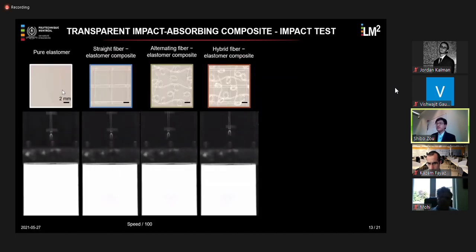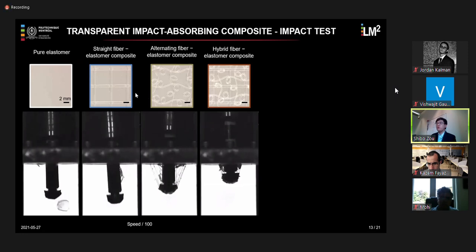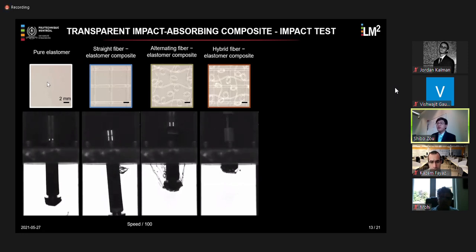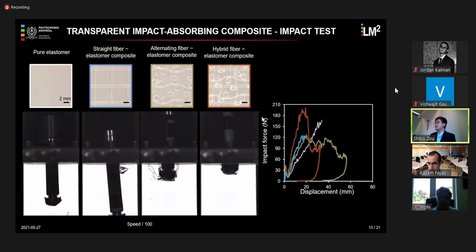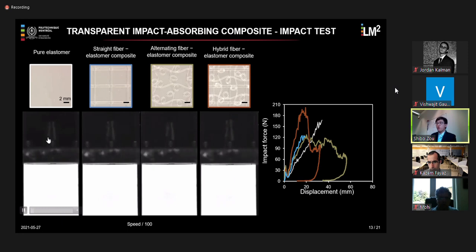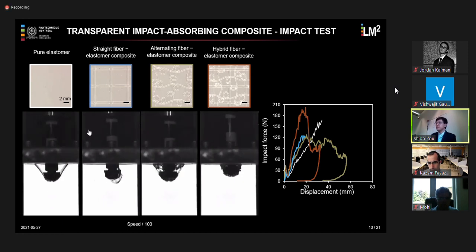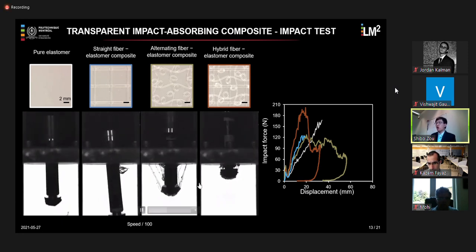And we tested 4 different specimens: the pure elastomer film, the one reinforced by straight fiber fabric, and the 2 other specimens reinforced by the sacrificial bonds-based fibers. In the meantime, we were also able to measure the impact force and the impact displacement. As you can see here, the falling dart penetrates both the control specimens, and it was successfully caught by the sacrificial bonds-based composite specimens.